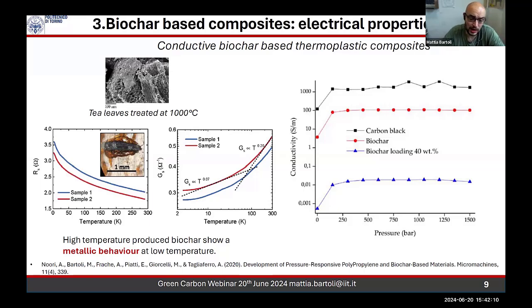Below it, you have a conductive biochar that is not so performing. At 1000 degrees, you have a conduction that is appreciable and quite high. 1000 degrees means a lot of effort to reach. But if you do not think of the traditional biochar pyrolysis approach, the fast pyrolytic plants, but of an autocombustion setup, you can easily reach this kind of temperature. So nowadays, with the autocombustion process based on plants, we can think of reaching this temperature in a profitable way.